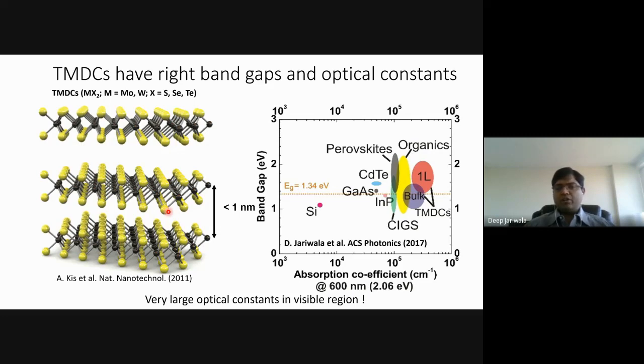It's a mineral. You can actually mine it from the ground as molybdenite. And it comes as this layered compound. Each of these layers has one sandwich of hexagonally packed metal atoms surrounded by two chalcogen atoms on either side. Because of these weak van der Waals bonds, you can exfoliate them. You can peel them out into individual atomic layers. Okay. So the reason we got interested in them is because they are semiconducting in nature.